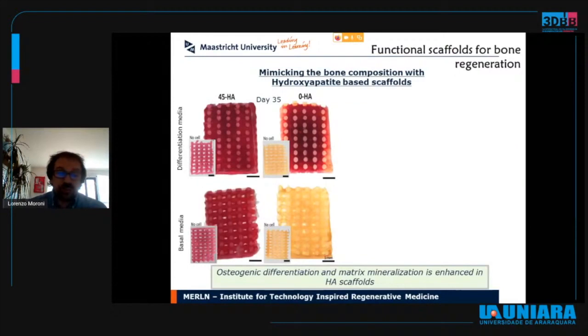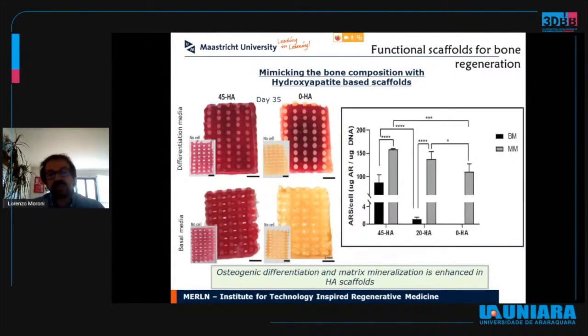From a mineralization point of view, which is of course important in terms of bone tissue regeneration, we also saw that with 45% of hydroxyapatite included in the scaffolds, we had not only a higher amount of mineralization in mineralization media, which is to be expected, but also, interestingly, in basic media. So again, showing the possible osteoinductive capacity of this kind of scaffolds.